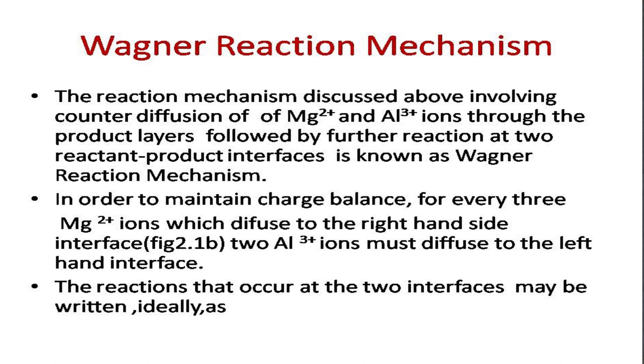Now, when such a reaction takes place through the diffusion of magnesium and aluminum ions through the product layer, followed by further reaction at the two product interfaces, such a mechanism is known as the Wagner reaction mechanism. I repeat, when a reaction takes place through the diffusion of magnesium and aluminum ions through the product layer, followed by further reaction at the two interfaces of the products, such a mechanism is known as the Wagner reaction mechanism. This is very important.